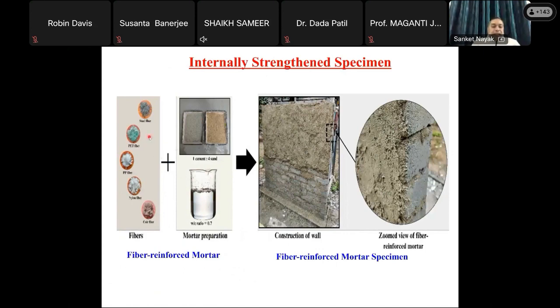And you can see these are the different fibers. They are added with the cement, sand and the water. Then the plastering is done. Before that, in the bond, it is also provided between the head joint and bed joint, and then the plastering is done. This is for all the cases. So what is the volume fraction? That has been optimized with respect to the compressive strength and the flexural strength, and we have to strike a balance between the compressive strength, the flexural strength and the workability, because if you add the fiber to a certain extent, the strength may increase, but after that it will reduce as some voids will form. So that optimization has been carried out to find the final ratio.